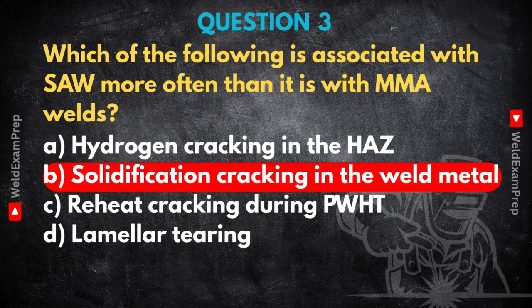MMA, on the other hand, usually has smaller, faster cooling weld pools, so it's generally less susceptible to that specific type of cracking. Now, hydrogen cracking can happen in both, sure, but it's often more strongly linked with MMA, especially with certain electrode types if preheat isn't right. Reheat cracking is a PWHT issue, and lamellar tearing relates more to the parent material quality itself. So for SAW versus MMA, solidification cracking is the key difference here. That's really clear. The large pool and slow cooling in SAW really set the stage for it. I've heard stories about just a tiny bit too much sulfur turning a potentially strong SAW weld into a problem.